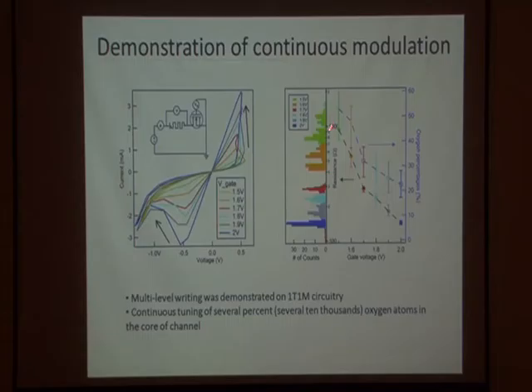We corroborated this by, these are statistics for the different states that we get here. I asked Feng, when he first showed it, he started going sequentially, 1.5, 1.6, 1.7, 1.8 until 2. And I said, Feng, we don't know, maybe it has to do with the order that you do this. Feng never complained, so I said, okay, you're going to randomize this and do the same experiment in a random order, and let's compare so that we know there's no hysteresis. We got the same data. It laid right on top of everything we already had.